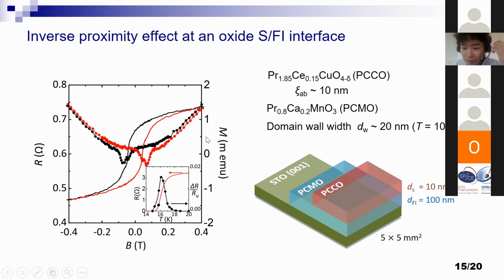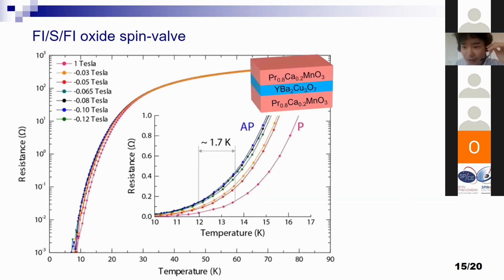And we used PCMO as a ferromagnetic insulator and observed this TC switching. And we couldn't observe this effect for YBCO because YBCO has a short in-plane coherence length. But if we prepare out-of-plane exchange coupling structure, so if we prepare tri-layer structure, we observe the very large TC switching. So here we have two ferromagnets, so we can control the exchange field along the out-of-plane direction. And depending on the magnetization orientation of these two ferromagnets, we can control the amplitude of exchange field inside YBCO. And we can observe a big TC shift using this structure.